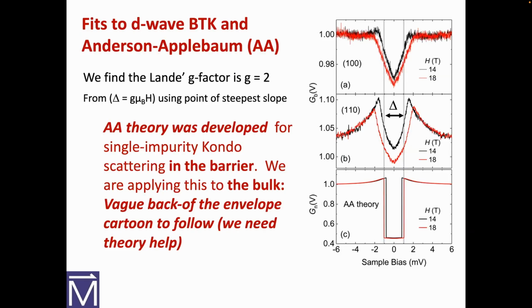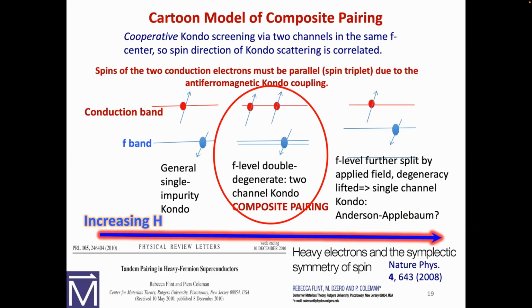So now I'm going to make a couple jumps and make some conclusions, in which case you can all disagree, but that's fine. This is a cartoon model that's kind of based on Rebecca Flint and Piers Coleman's model, which I'm not sure they're convinced of, but I thought it was sort of interesting. As we all know, there's the Kramers doublet. I've read this paper about 30 times, probably a lot more than that. It's very theoretical, and this is sort of a heuristic interpretation. So we have a Kramers doublet, and what if you can have two electrons scatter off of the same f level because you have a doublet? And what if that creates some kind of coherence between the electrons? If that is the case and you apply a magnetic field, that splitting will be a Zeeman splitting and grow linear with applied field.